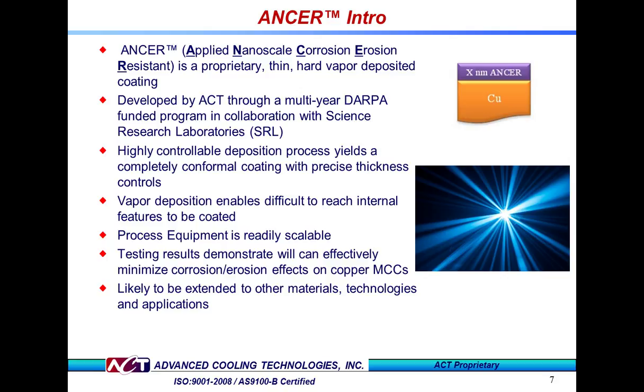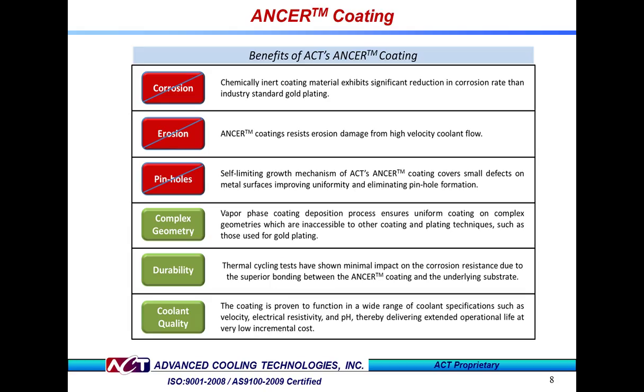ANCER uses a chemical vapor deposition process to apply a thin, nanoscale conformal coating across the surface substrate. The readily controlled vapor deposition enables the ANCER coating to be uniformly applied on difficult-to-reach, high aspect ratio internal features of microchannel coolers. Further, the deposition process is readily scalable to handle more or larger parts. Our testing of the ANCER coating has shown it to be very effective in preventing corrosion and erosion effects. We'll share our results with you today. And testing has commenced on aluminum to determine if the same benefits can be realized there as well.